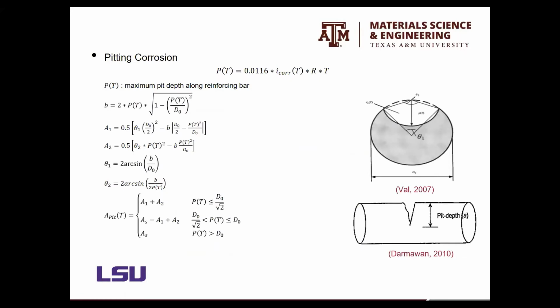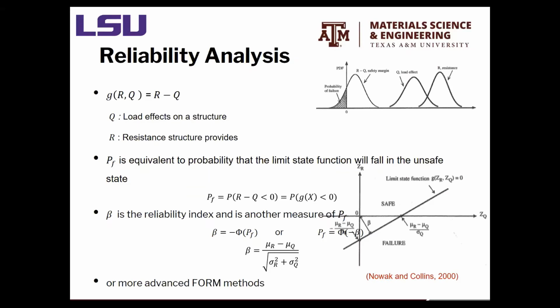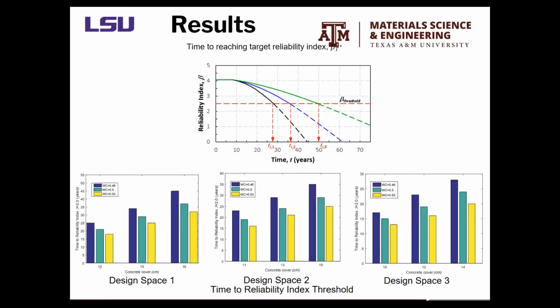It's based on the rebar. It's not only general corrosion, but this is the shape of the pit. Of course, it's an ideal geometry shape. We are doing this experimental study. We built the model, and this was work from LSU that built the model based on the literature, but now we are putting the model in terms of validation with the experimental results based on the localized attack. This is the reliability approach that was performed, and these are some results based on the literature.